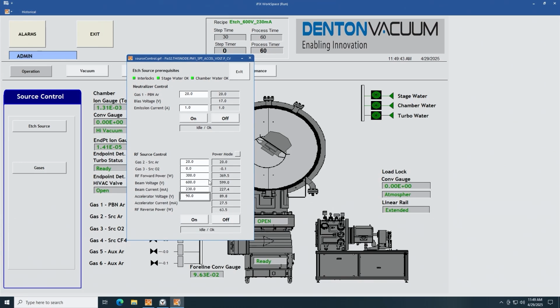So after ignition, it's going to slowly adjust the RF power to the power required for the current you asked for. I told it to start at 300 watts, so it did, and it got about 100 and some milliamps. And then it had to ramp up slowly to 370 watts in order to reach 230 milliamps. So you'll see here the reflected power is quite high. It's 60 watts. And the reason for that is because as this tool accumulates hours, the etch products are actually coating the inside of a quartz chamber inside the source, and that is reflecting the RF back.